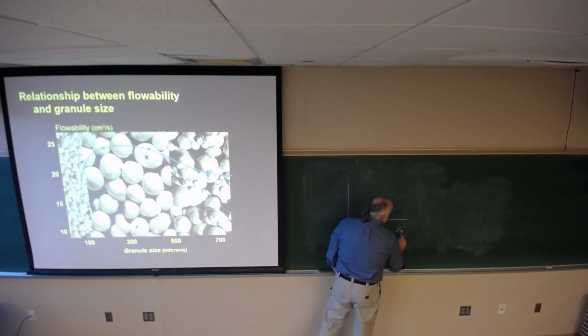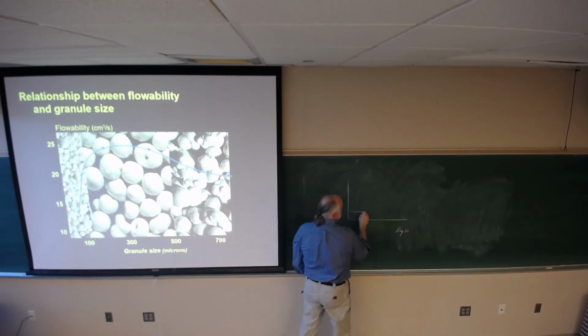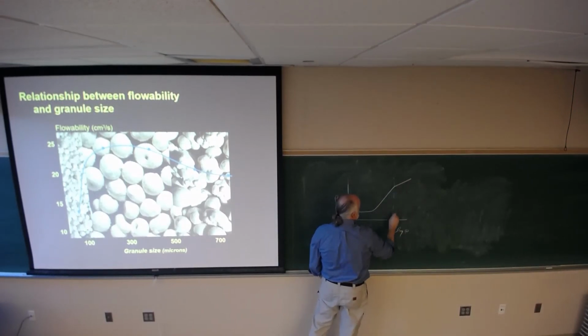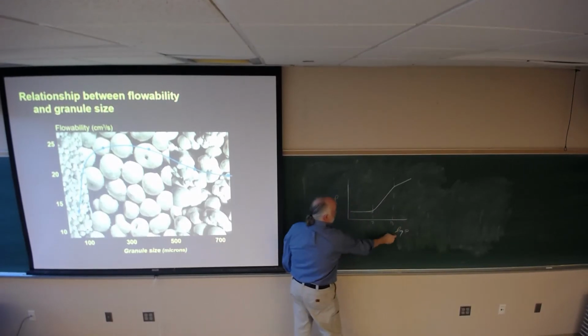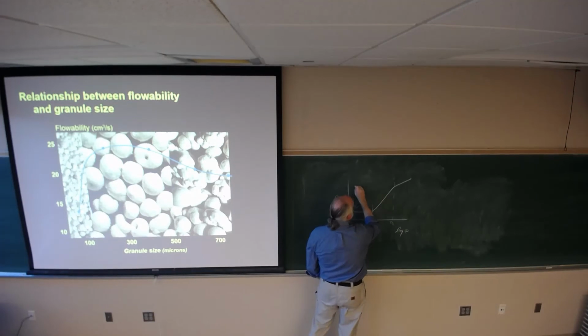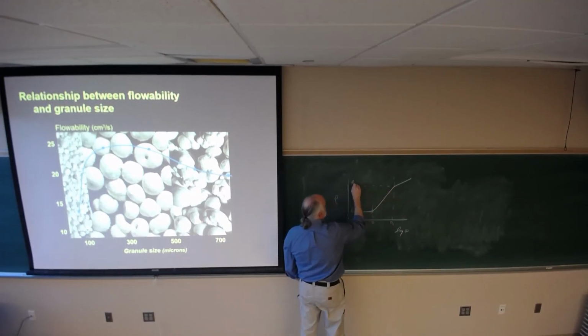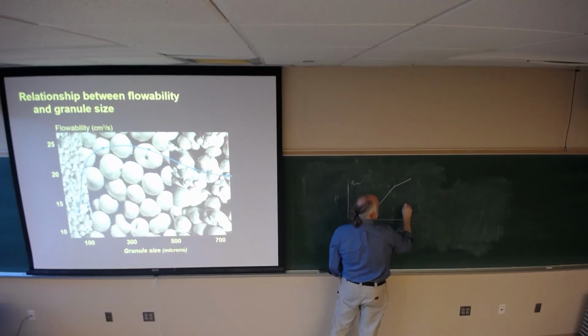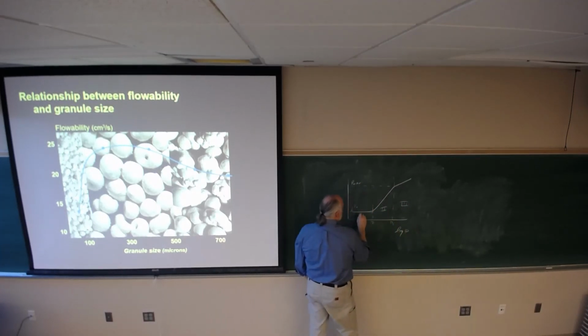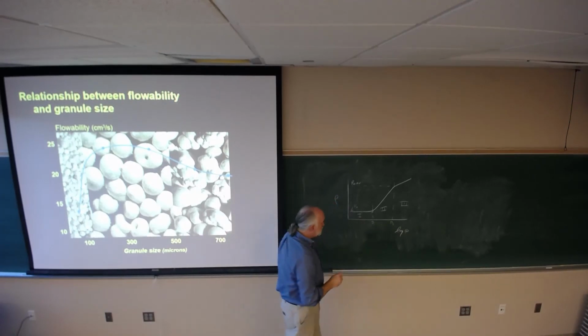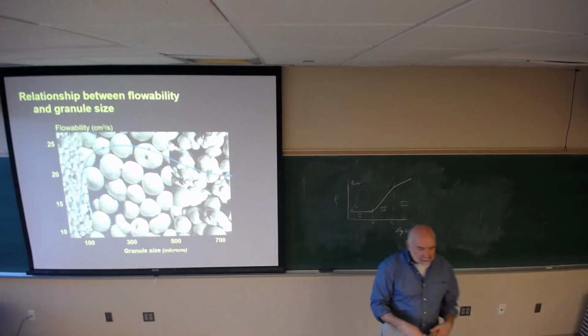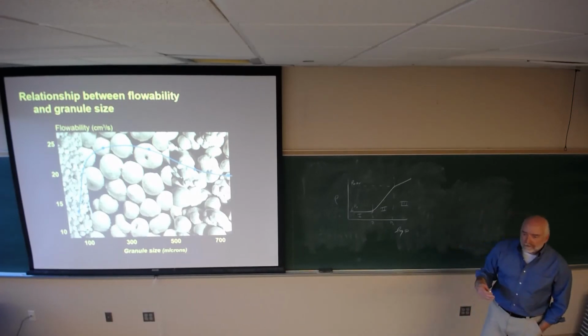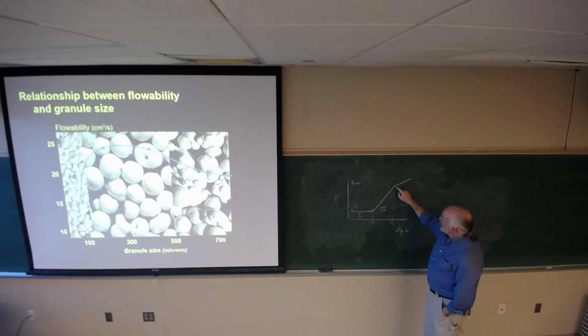Okay. If I look at log pressure, I look at density, I get 3 regions. Okay, and so I can extrapolate this region down to P1, P2. Log pressure, remember, this is packing density of the powder, and then this is my maximum density. This is region 3, region 2, which are compaction region, region 1, which is simply the way the material behaves. P1 is actually the strength of the granules in the bed. There's no change in density with an increase in pressure up to a certain point. And then this is actually a spring back. This is elastic energy. So this is plastic